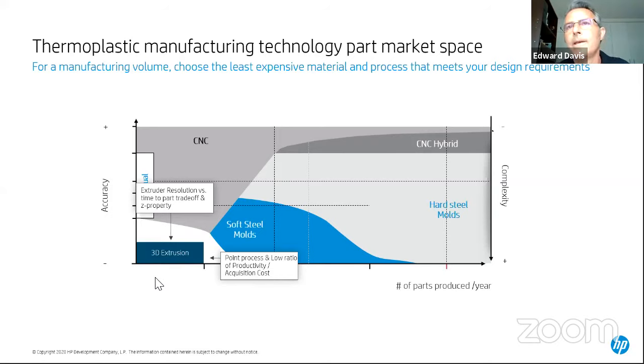So then, having said that, what we've done is, in fact, looked at powder bed fusion. For those of you who are not familiar with multi-jet fusion, I'm going to introduce laser sintering first, because what we've done is taken some of the trade-offs of laser sintering and improved upon them. So laser sintering, it's the same problem scaling to the right. It's a point process, and they have a low ratio of productivity divided by acquisition costs. They're a bit faster than material extrusion, but the fact of the matter is the same story.